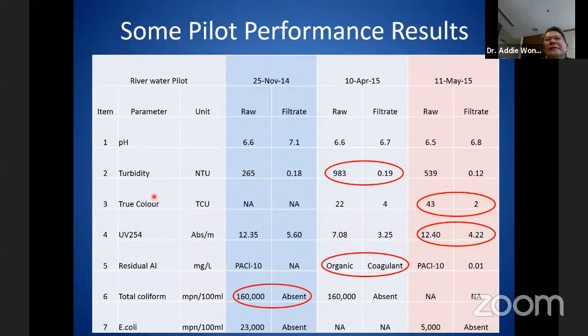I want to emphasize that with coagulant assistance, the true color is removed very significantly, from 22 to 4 or from 43 to 2. If we use any membrane without coagulant assistance, the true color will be about the same. Remember, if we do a true color test in the laboratory, we use a 0.45 micron membrane to filter before we do the color test. So it's the same principle. Without coagulation, the color removal will be very limited.